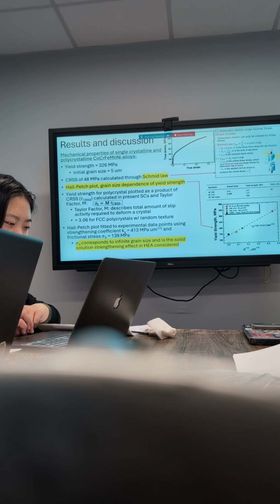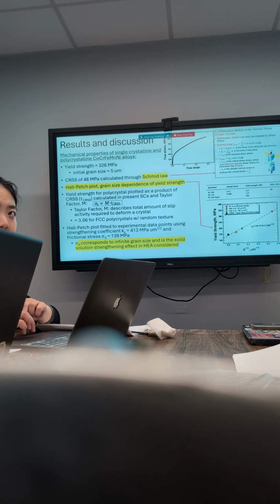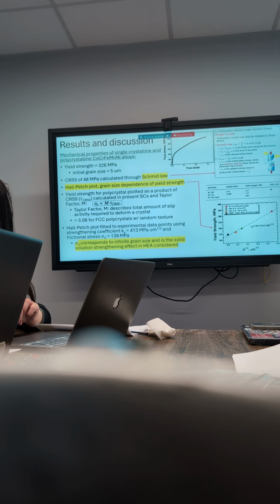Then they go further into mechanical properties. They found the yield strength for the polycrystalline alloy was 326. They use Schmid's law to calculate CRSS, and I have included here some stuff about it, which is basically the shear force along the slip direction divided by the area of the slip plane. Yeah, it might be good to review some of that stuff.